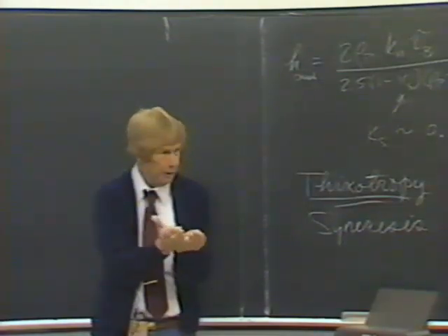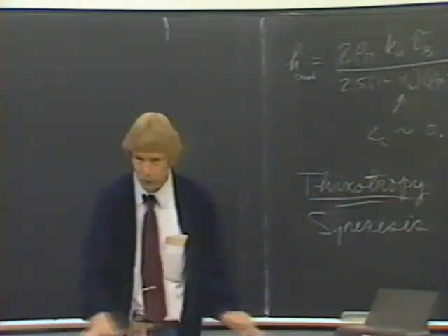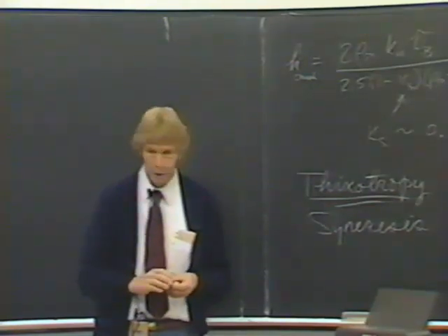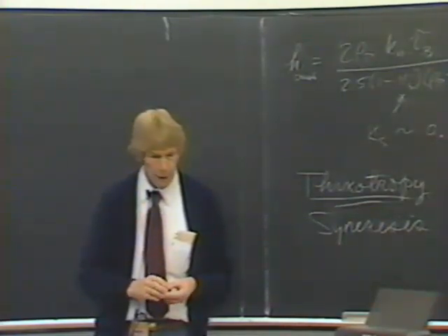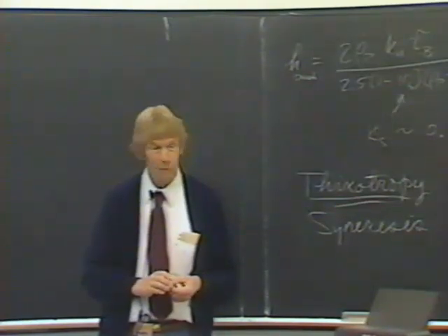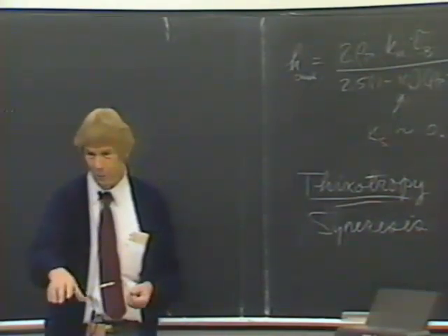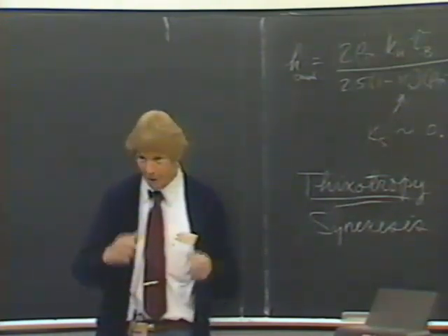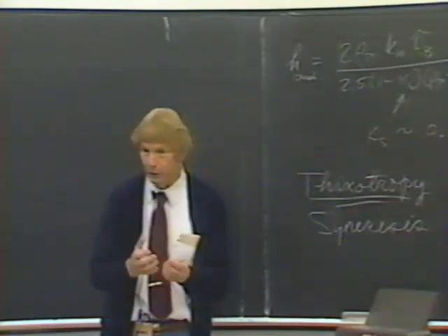Well, what this is all leading up to is that a long time after the project was finished, you could go out there and still see those lumps of sediment on the bottom, even though the whole area was sand because the fines couldn't reside there. These lumps were strong enough. The gel was strong enough so that they stayed on the bottom. They're long gone now, of course, but they lasted quite a long time, indicating that even though the material wouldn't deposit there normally, when it forms a gel, it's stronger, and that will resist intense wave action out there.